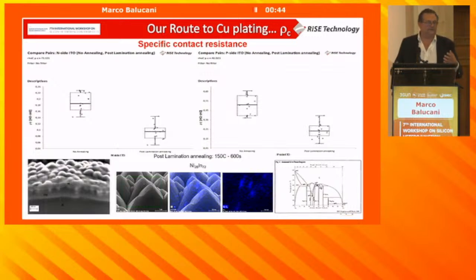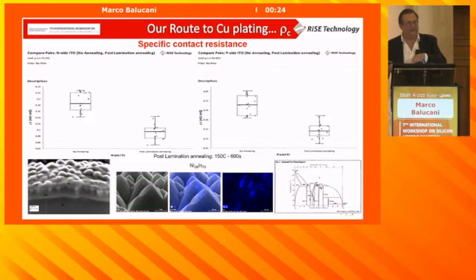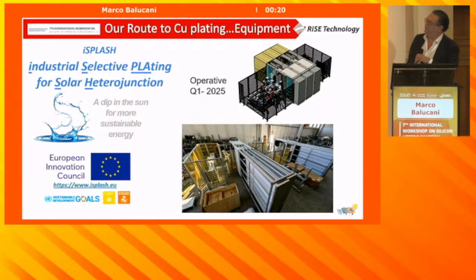And this is very nice because it decreases the resistivity, and we see a decrease after the post-lamination of the specific contact resistance. This is because we form the sintered metallic, and that's the reason why you have really good adhesion. Also, when you pull out, you still see ITO, but you find the nickel because you form the sintered metallic.